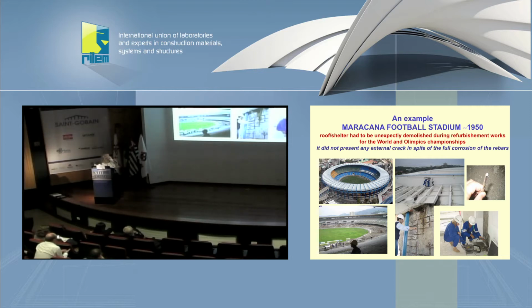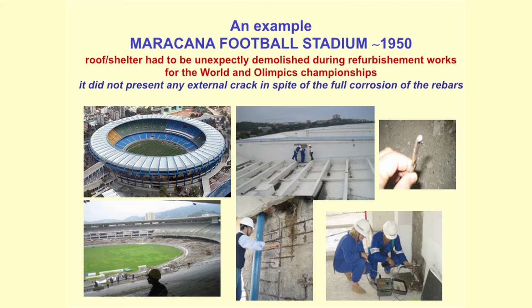What did Ennio do? He was trying to make a detailed diagnosis using ultrasounds and the corrosion rate meter, and he detected very weak zones non-destructively and also high corrosion rates, and that is when he suspected that the problem was much bigger. We also realized that the steel is not only corroding and losing section, but you can break the steels with your hands. This is one that we broke there because it has been embrittled, and corrosion can embrittle the steel when you have losses higher than 25%, and this is a hidden problem that we shouldn't forget when we are repairing the